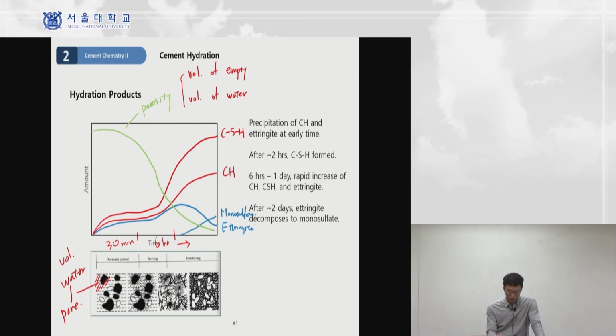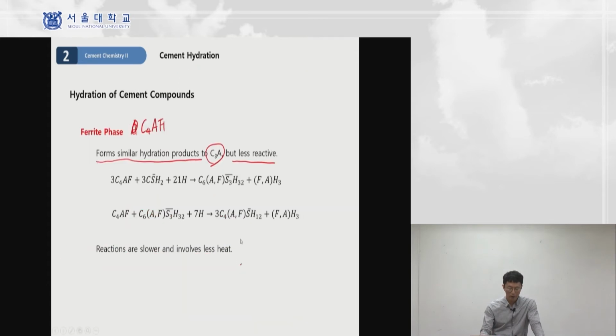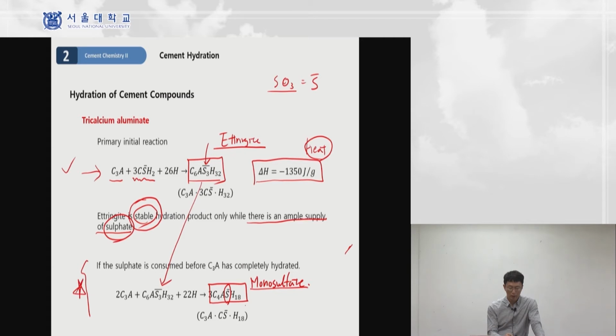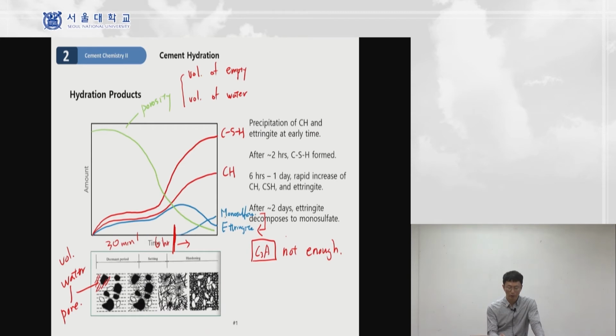So if you think about this monosulfate formation, if the C3A is not enough, then at some point here, there's a decrease of the ettringite phase, but there's an increase of the monosulfate. So this is the case. If sulfate is consumed before C3A has completely hydrated, this additional hydration goes on to produce monosulfate from ettringite. So this is the point. This is the reason why we have to see this kind of monosulfate production and the reduction of the ettringite crystal.